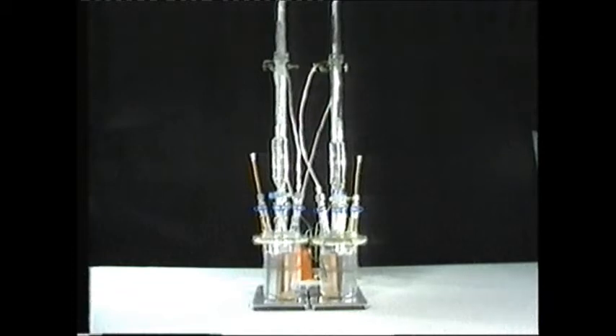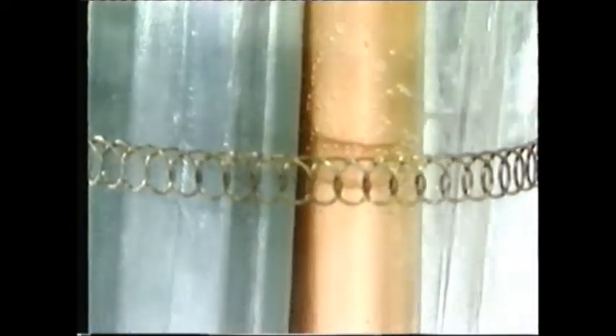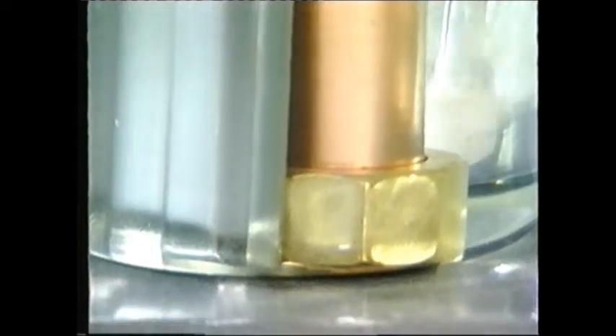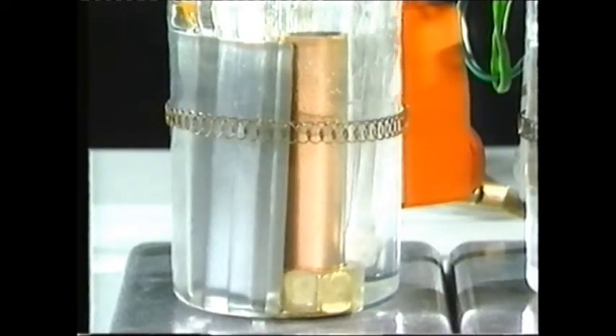Two containers of ordinary tap water were heated. The temperature was 60 degrees centigrade. Remember, corrosion increases with temperature. Identical steel plates and copper tubes were placed in each beaker, but a correct amount of Fernox corrosion proofer was added to the beaker on the left.